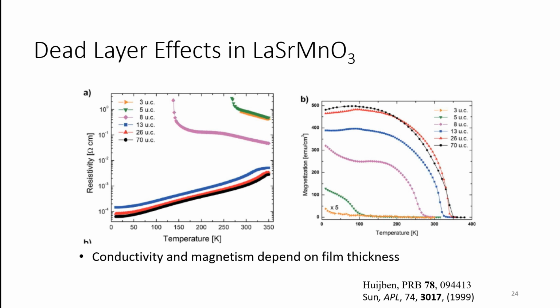All right, so this wasn't a discovery we made. It was well known when I was in high school. Well, I'm not dating myself, but for LSMO films, if they were very thick, they were nice, they had low resistivities. The resistivity went down as you reduce the temperature, which is what you expect of a metal. If you made them really thin, so 5 unit cells, then the material became too insulating to measure even close to room temperature. And the same thing happened with the magnetic moment. So this was called the dead layer effect, where if your material was too thin, it was effectively dead, right? So what we like to do is understand why it dies and hopefully resurrect it from the dead.